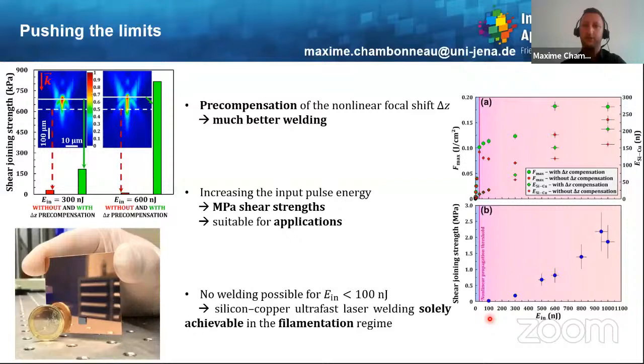the nonlinear focal shift. Besides, here on the top, one can see the evolution of the maximum fluence reaching the interface, as well as the energy deposited at this interface, or the energy reaching this interface, as a function of the input pulse energy. And one can here again see that precompensating the nonlinear focal shift leads to enhanced energy deposition.